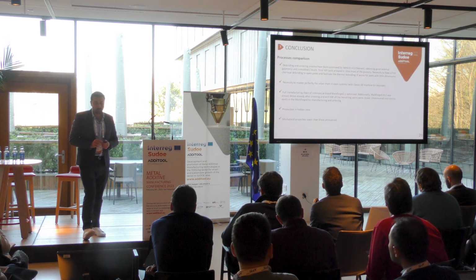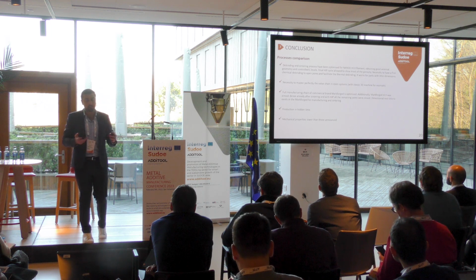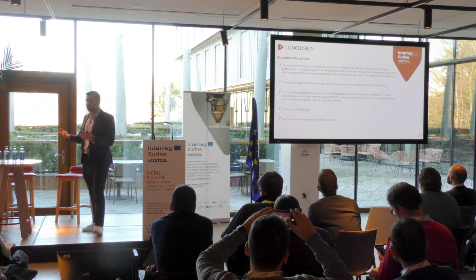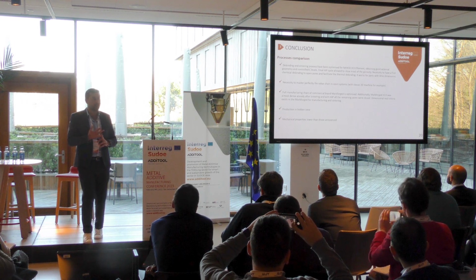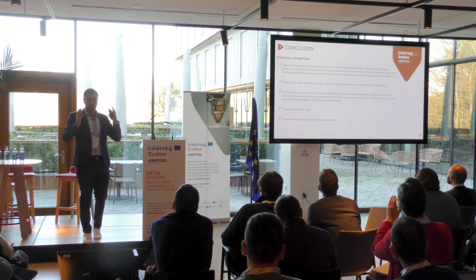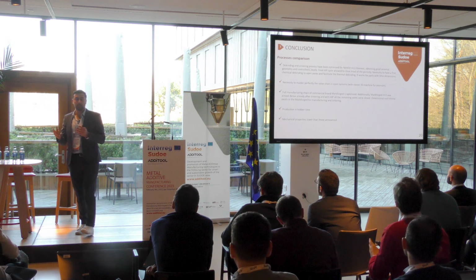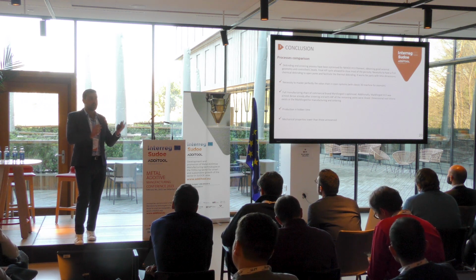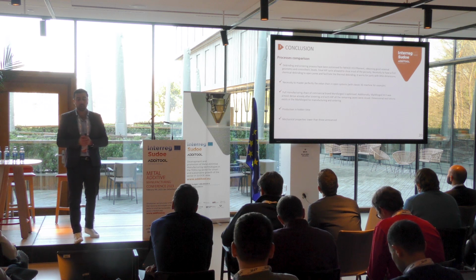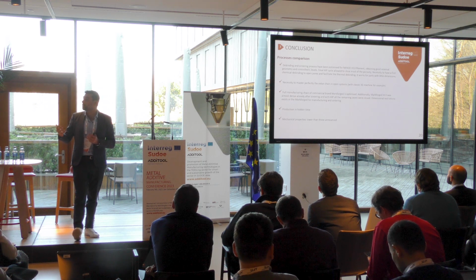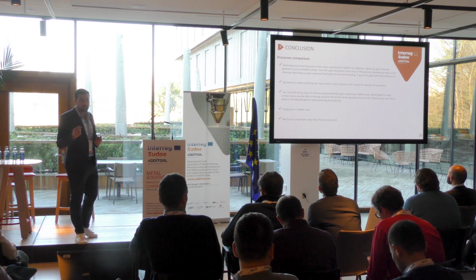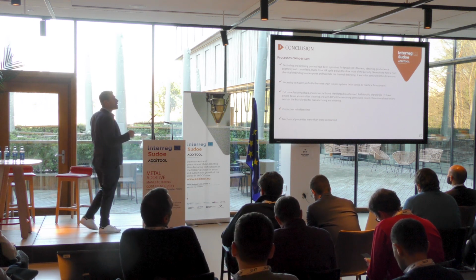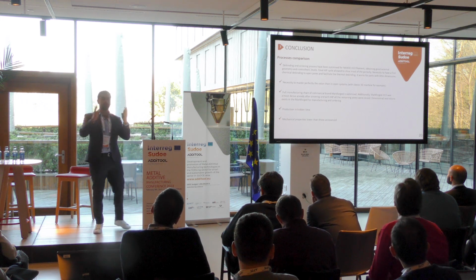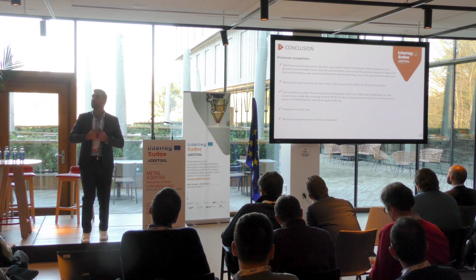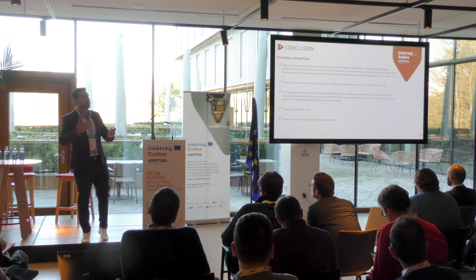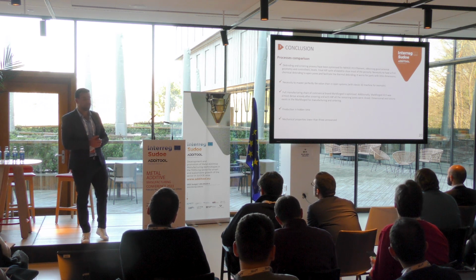In terms of conclusion, according to this pilot, the debinding and sintering process have been optimized for the NanoE H13 filament, obtaining good external geometry and controlled carbon level. A final hot isostatic pressing can close most of the porosities, but it is necessary to have a first chemical debinding to open some pores to facilitate the next thermal debinding.